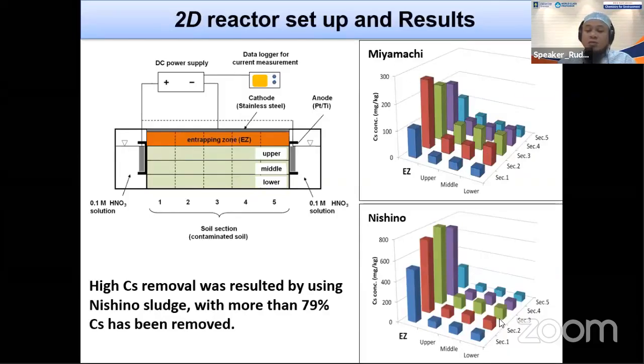But for the Nishino, since the Nishino also contains the activated carbons, most of the cesium concentration is deposited in the entrapping zones. So in such a configuration, it is already proved that when we use the 2D reactor system with combined entrapping zone, here using the Miyamachi and Nishino, they can absorb the cesium maximally in the entrapping zones.